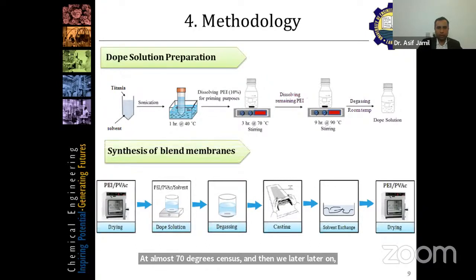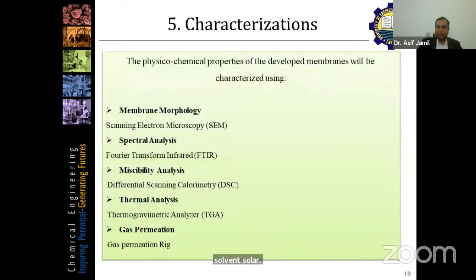For the membrane synthesis process, we use the phase inversion method so that we can produce asymmetric membranes, and we use flat sheet membranes. We cast the membrane and then put it in the non-solvent, which we use as water, and then we simply dry the membranes. Once the membranes are ready, we go through these characterization techniques so that we can see the structure and the performance of our membrane.